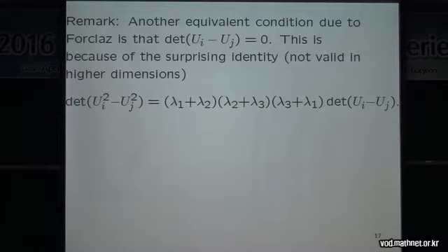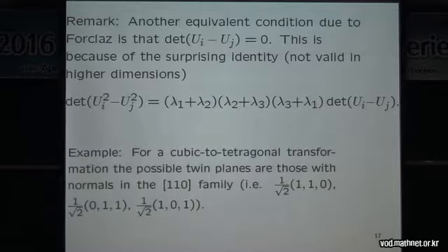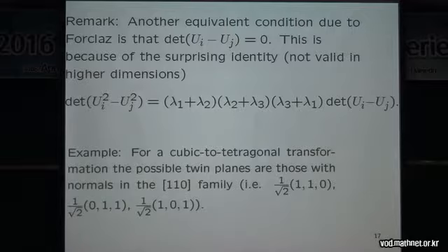So if you apply this to a cubic to tetragonal transformation, you find that the possible twin planes are those in the 110 family. So these three are typical 110 planes. And that's what we saw in the high-resolution picture, because the plane was vertical and it bisected the cubic axis. So everything seems satisfactory. Okay, now